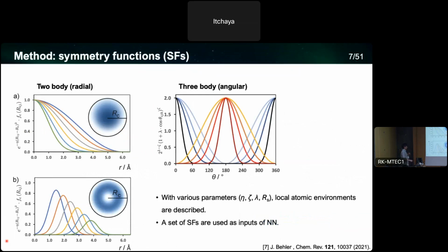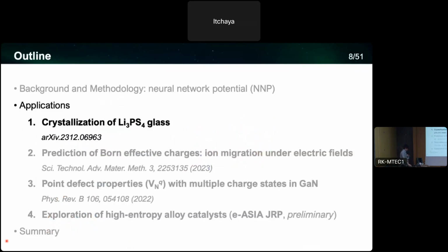Sorry, I forgot to show what the symmetry function looks like. These are two-body terms. By changing the parameters, the Gaussian function can change the decay factor or shift peak positions. And also for the three-body term, we can change the shift angle, the peak angles, like at 180 degrees or 0 or 360 degrees. So we prepared different sets of parameters to represent the local atomic environment. This is the brief overview of the neural network potential.